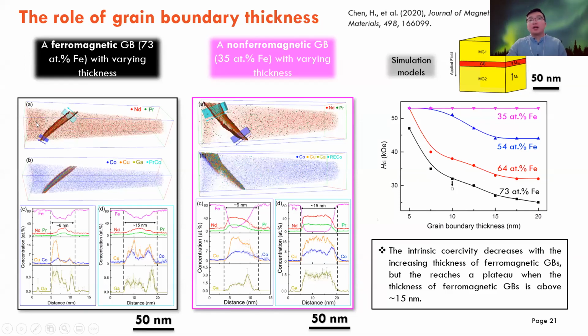Besides the grain boundary composition, the grain boundary thickness is also a very important factor affecting the coercivity. And the same, we can see the grain boundary is actually not uniform in thickness, varying from 6 nanometers to 15 nanometers. Based on the simulation, we know that if the grain boundary is thick enough, about 15 nanometers, the coercivity reaches a plateau. But if it's thinner, then it strongly relies on the different concentrations of iron, and the reduction will show different behavior here.